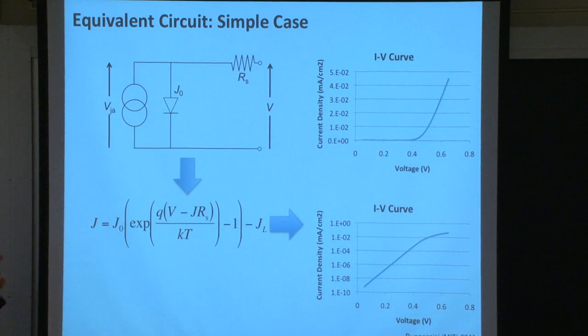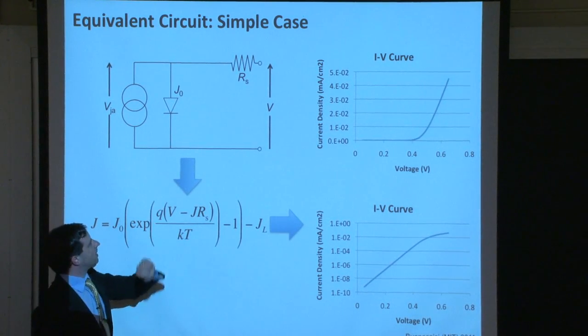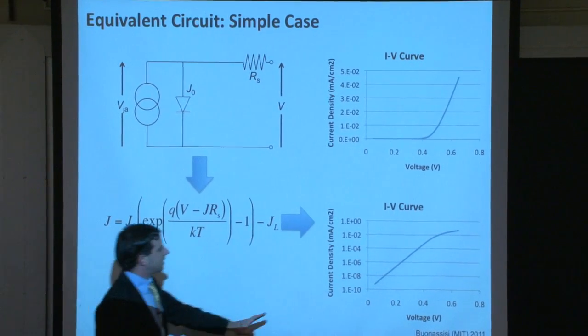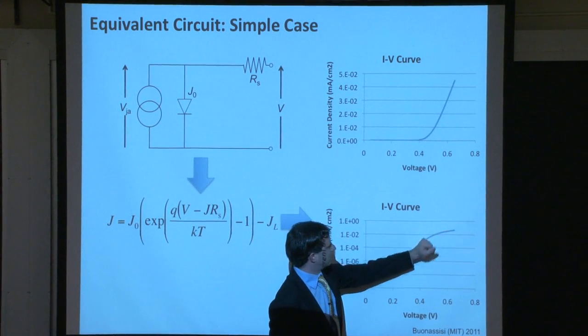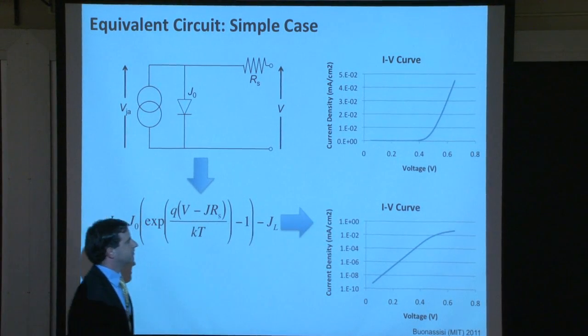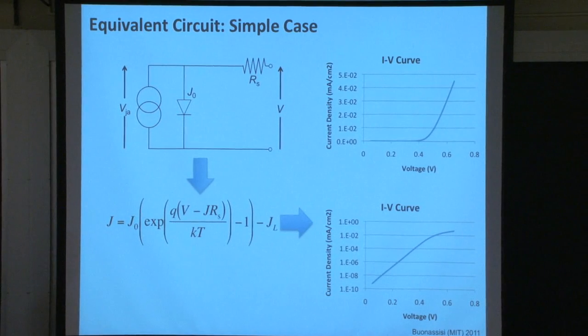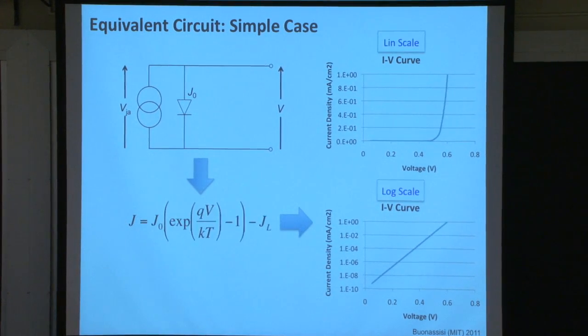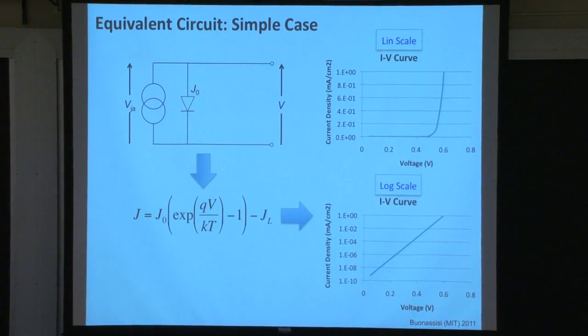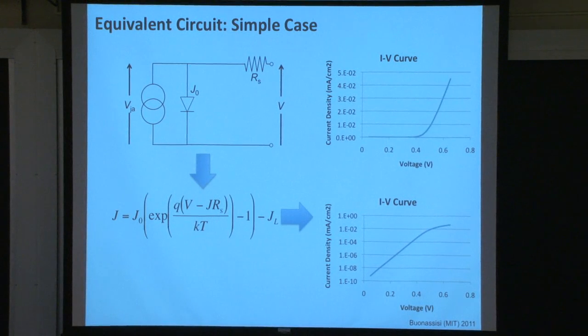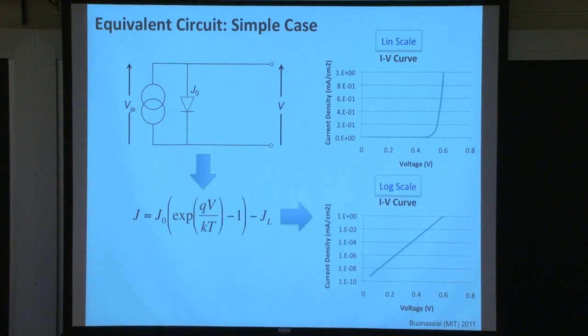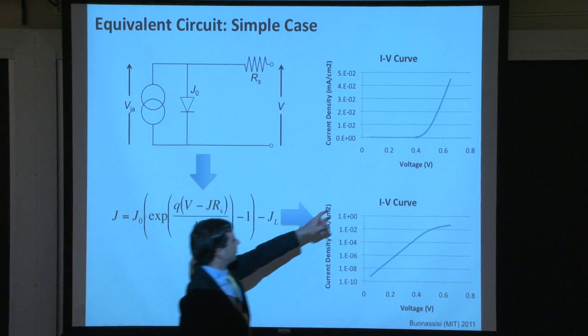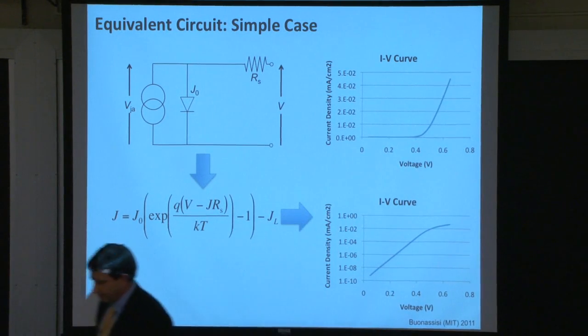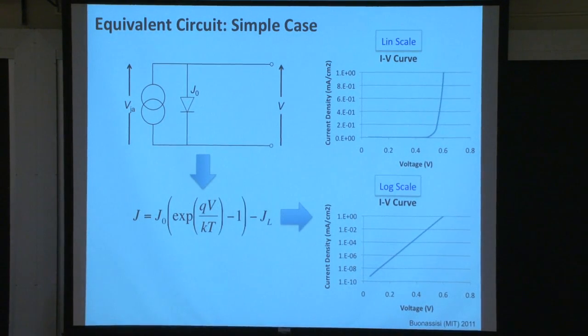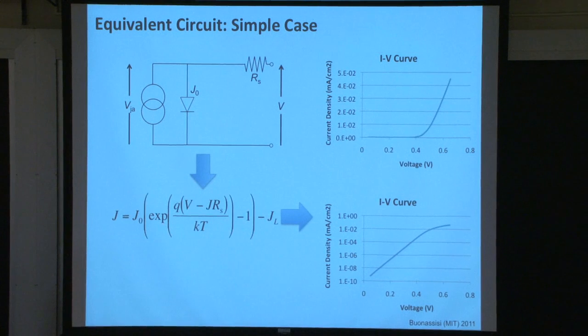Not so when you introduce a series resistance. So when you have that series resistance component, now at higher bias voltages, you begin to be series resistance limited, which causes the fill factor to decrease. And you can see that by going back and forth between these two slides. High fill factor, no series resistance. Lower fill factor, higher series resistance. Especially if you focus right here at this point, you can really see the decrease of fill factor as a result of adding the series resistance component.